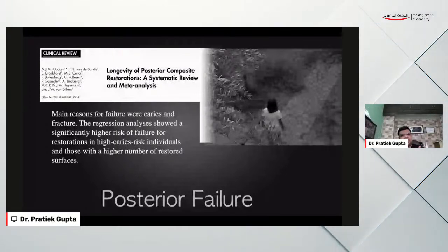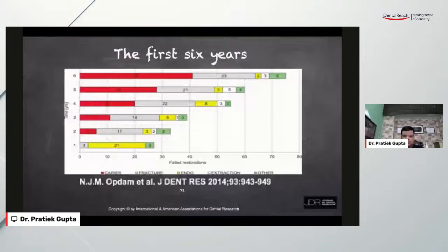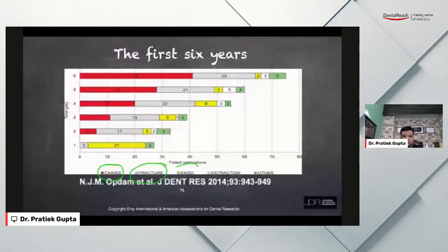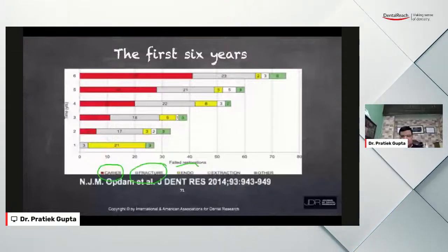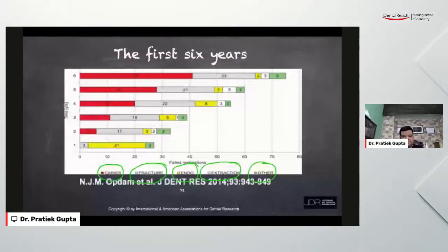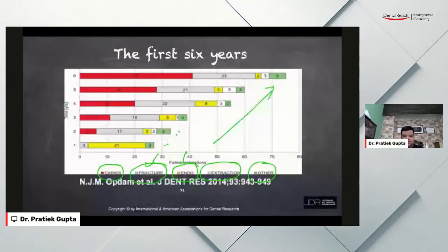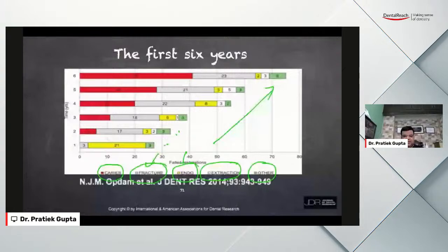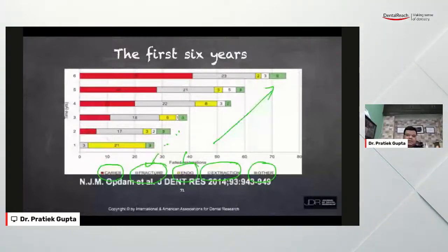Main reasons of posterior failures or anterior failures in the first 6 years, if you look at this graph here: if you see red, those are caries. If you see the gray ones, those are fractures. Then they went towards endodontic procedures, extractions, and others. But if you look at what happens in the first 2 years, it is mostly fractures or endo. That means the bonding fails. Over a period of time, this can be operator errors where you've not bonded properly, where you've not isolated properly, and this happens initially.